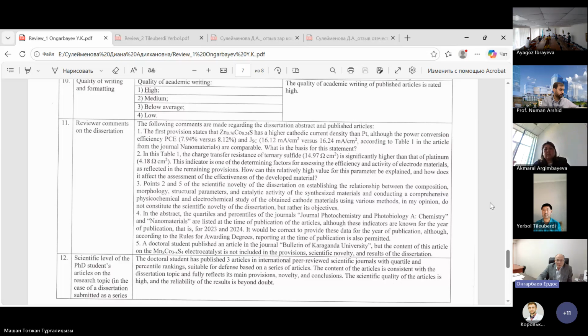Second comment. In this table, the charge transfer resistance of ternary sulfide, 14.97, is significantly higher than that of platinum, 4.18. This indicator is one of the determining factors for assessing the efficiency and activity of electrode materials, as reflected in the remaining provisions. How can this relatively high value for this parameter be explained, and how does it affect the assessment of the effectiveness of the developed material?